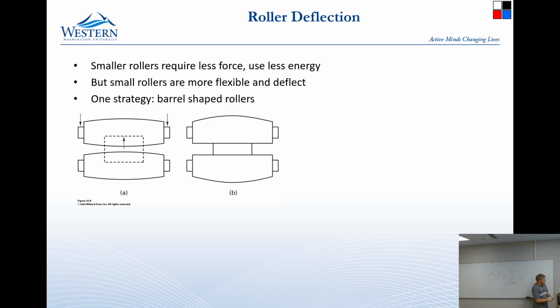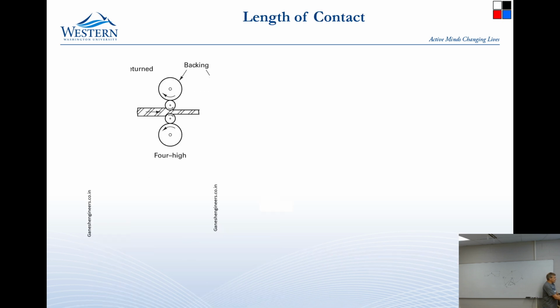That seems kind of cool, but it doesn't work if you're doing it over a really wide part. This only works for something that's fairly small. So instead what we do is we back up the roller with another roller. So if we have a little roller, we put a big roller behind it. Well, you can see that this 4-high roller is not going to be able to do a very wide part because the little rollers would just squirt out from underneath the big rollers. So we're going to have to do something better than that if whatever we're pressing is getting very wide.